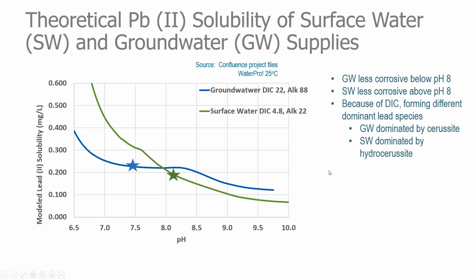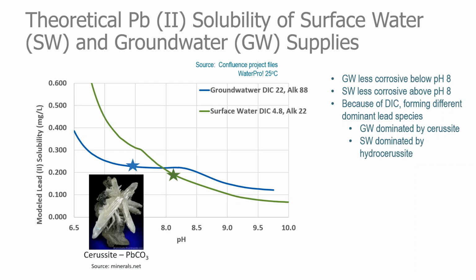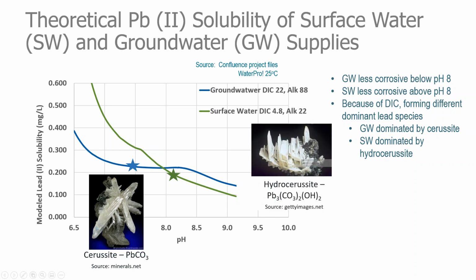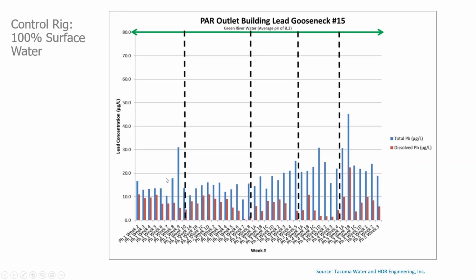But we're actually forming different lead species at the pHs because of the DIC. The groundwater is dominated by cerussite, which is a lead carbonate, and as you can see in this picture, it almost looks like quartz crystals. I took these from the internet. They're nice photos. And the surface water is hydrocerussite, which is a lead hydroxycarbonate, and it's much more of a platy, flat crystalline structure that Bofu also showed a photo of in his presentation. So we're actually forming different lead minerals depending on which water is being served. That's what the solubility modeling predicts. And in fact, that's what we saw in the pilot rigs, as we'll get to.